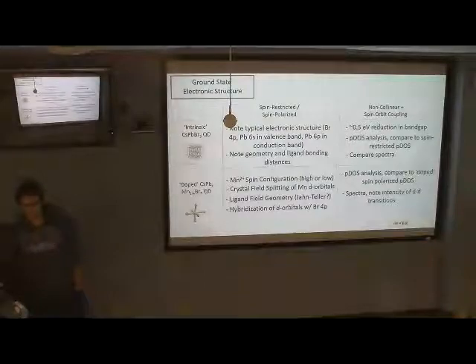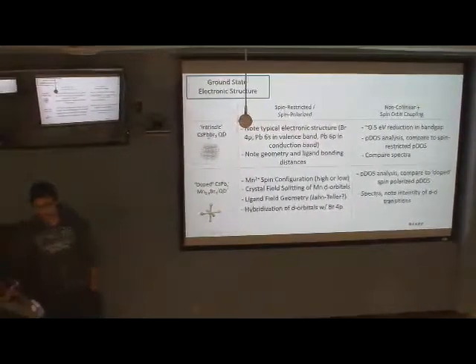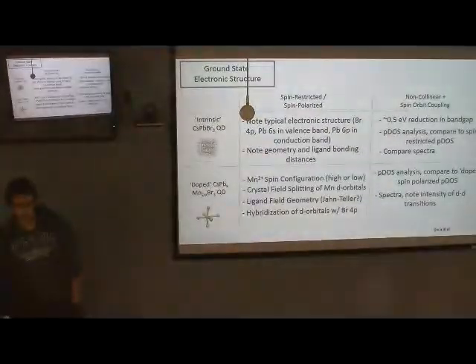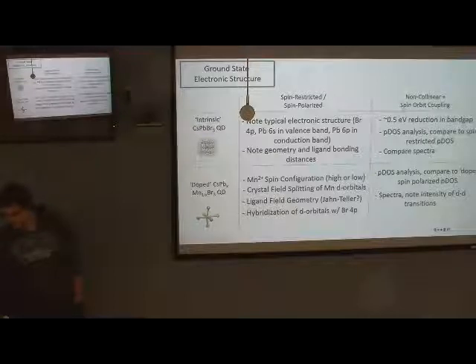And then once we optimize both of them, we do non-collinear plus spin orbit coupling single point calculations to include spin orbit coupling effects, because both lead and manganese have it. Lead has a large spin orbit coupling associated with it. Manganese has a smaller one, but it's still there. So to do accurate modeling of the photophysics, you have to include spin orbit coupling. So that's why we do single points for both of those.